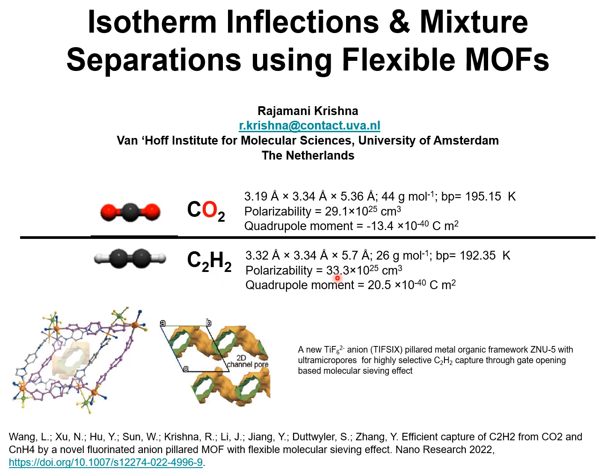C2H2 has a slightly higher polarizability. The quadrupole moments are opposite in sign and the magnitude of the quadrupole moment of C2H2 is slightly larger. In a recent paper in Nano Research published in 2022, it is reported that a pillared metal-organic framework ZNU-5 with ultra micropores has high selectivity towards C2H2, and the mixture separation is achieved through gate opening effects that also result in molecular sieving in favor of acetylene.